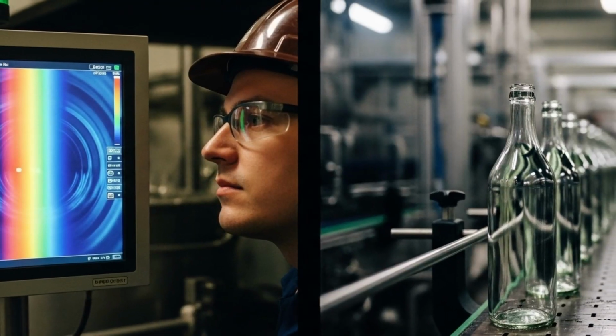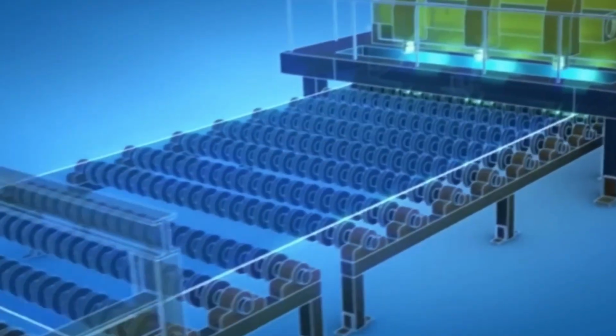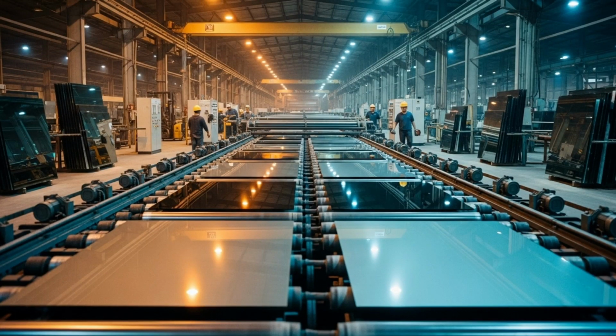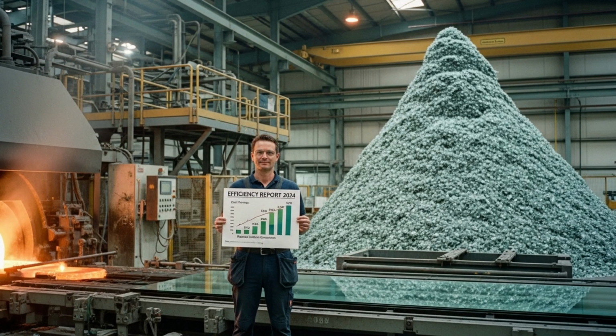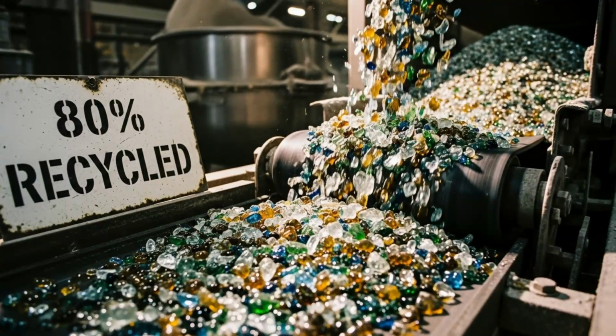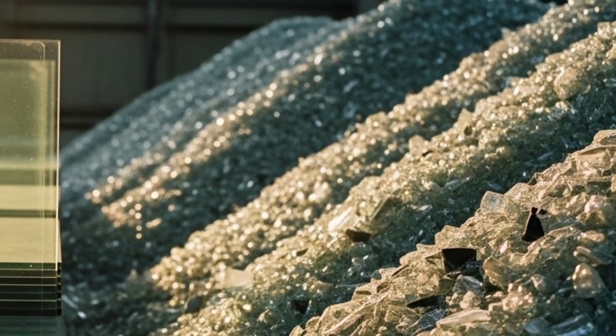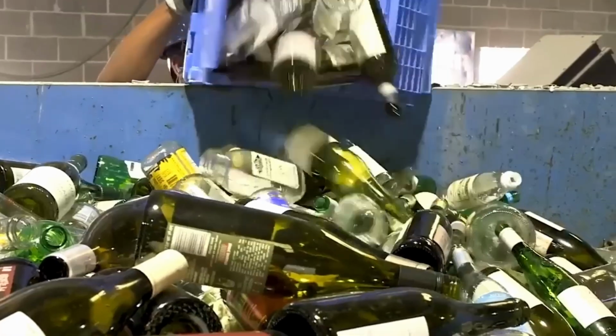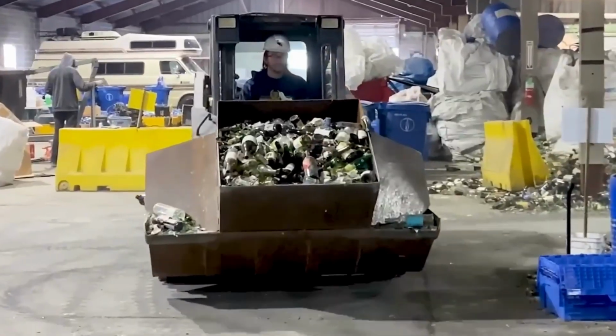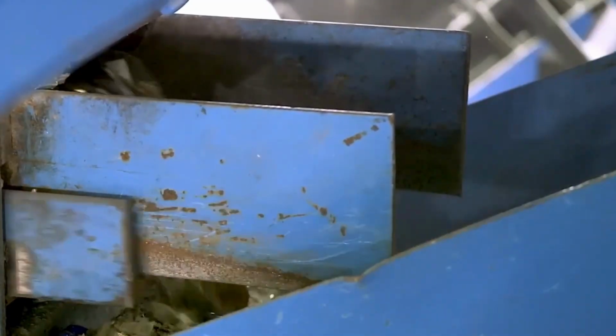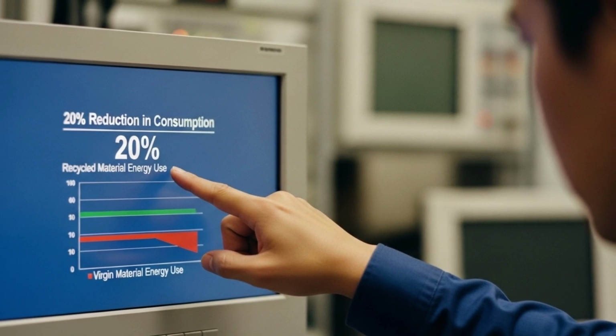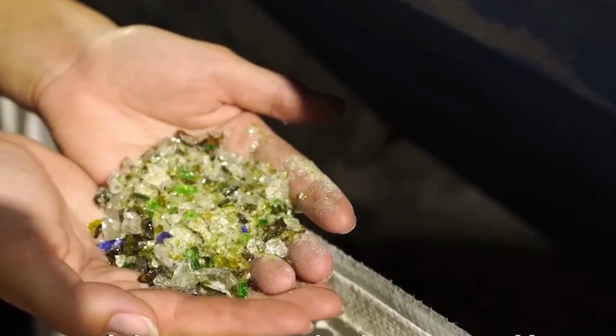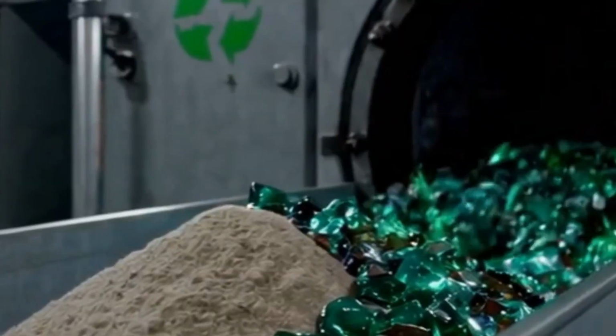Alongside container manufacturing, the plant also produces flat glass, used in windows, screens, and solar panels. Here, recycling plays a leading role. Up to 80% of the mix can be cullet, crushed glass recovered from recycling facilities. This strategy not only reduces raw material extraction, but also cuts energy use by about 20%, making the process more economical and sustainable. The recycled material is crushed, cleaned, and mixed with fresh sand before entering furnaces similar to those used for bottles. However, the shaping method is different.